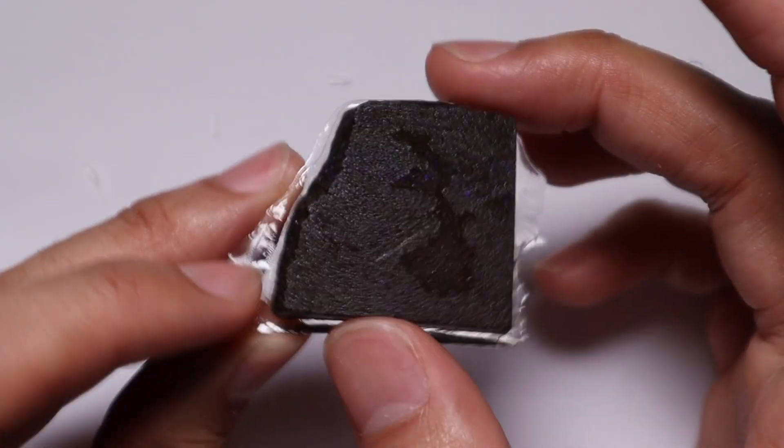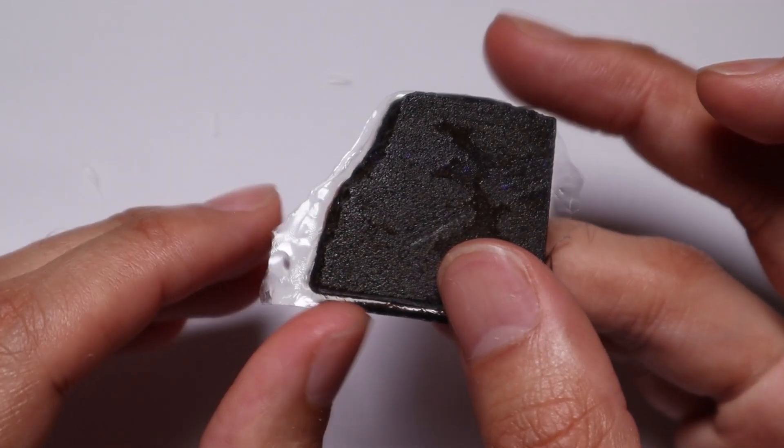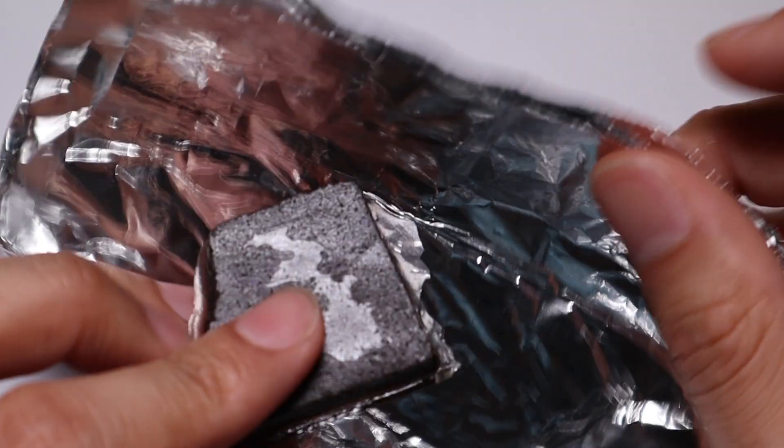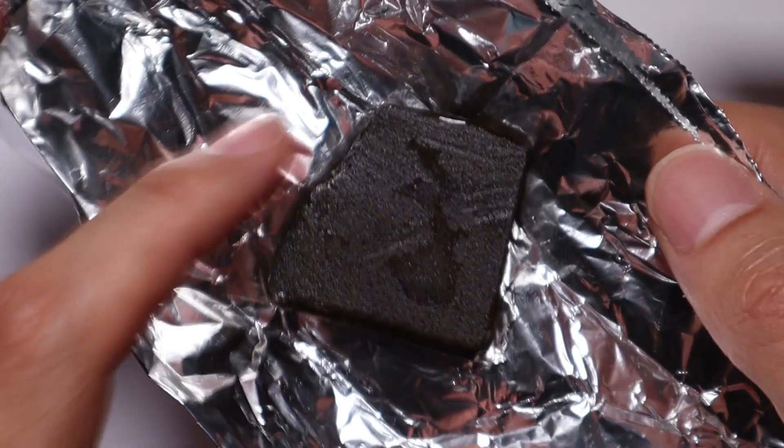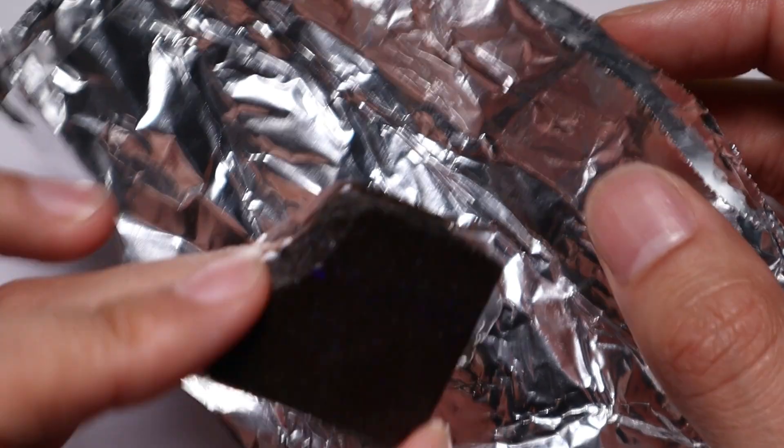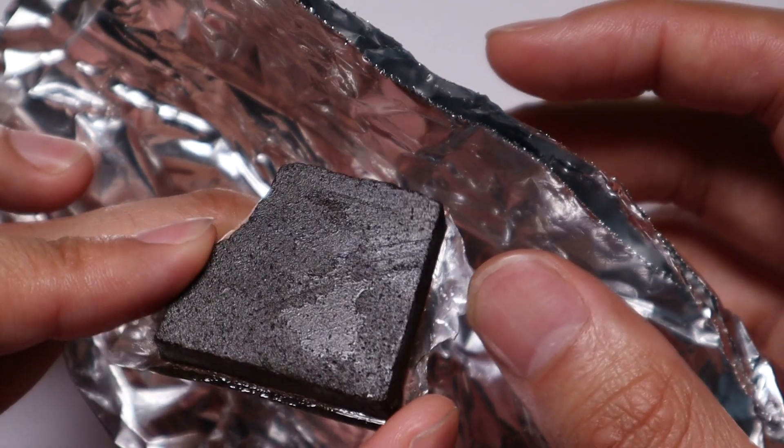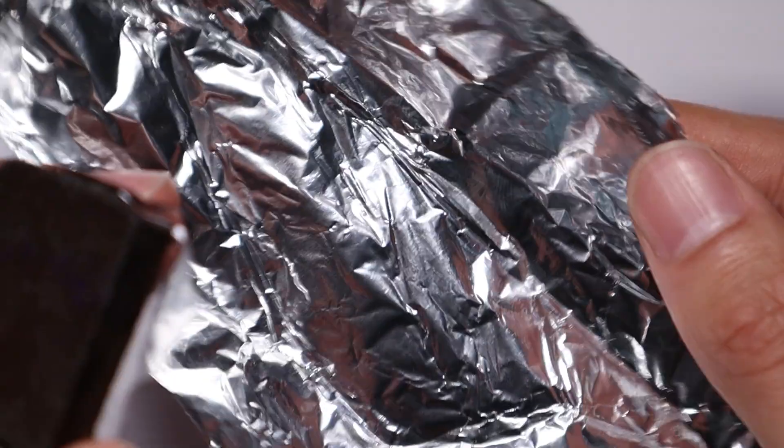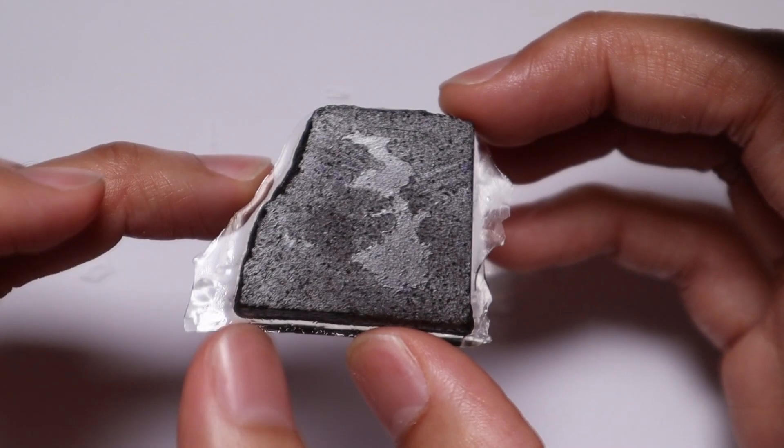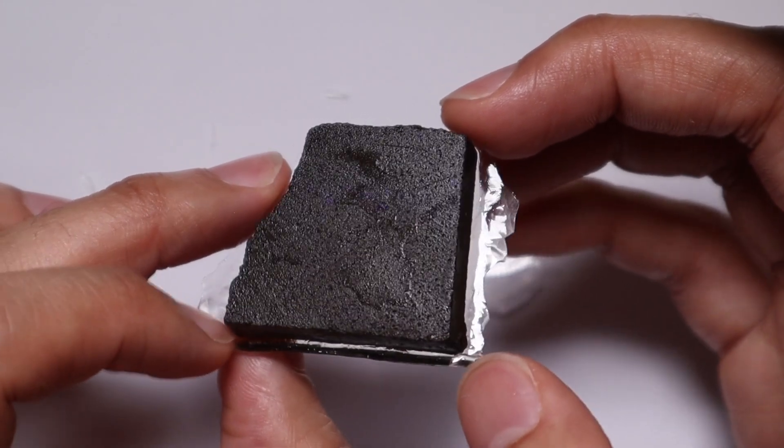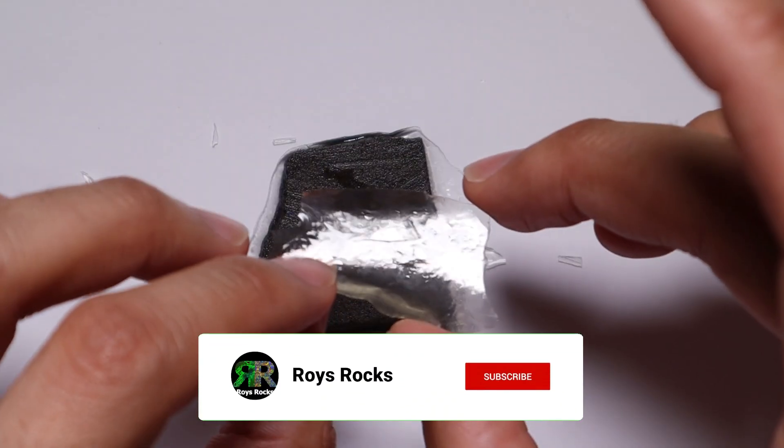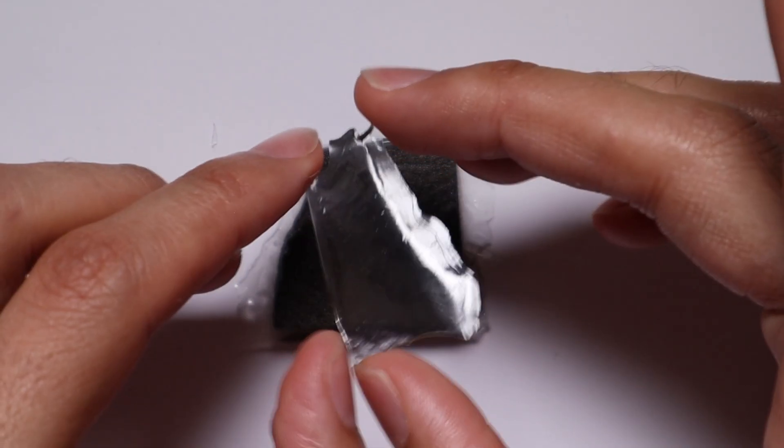It certainly does penetrate and it certainly does stabilize the stone. It's much harder and the treatment has definitely gone all the way through, making it really heavy. A little bit tricky and handling this is actually incredibly dangerous, because these edges are quite sharp and jagged. I actually think I've got some shards of it in my hands after doing those snaps. I should also mention, once you've got it in the foil and baked, if you find that it's stuck to the foil, just let it cool to room temperature and then it will just release itself. Don't panic and try to yank it off or anything. While it's hot, this is still a thermoplastic and so it's very grippy. Just let it cool all the way off and then just peel it off. You'll see that nothing gets left behind on the foil. It will very much stick to the rock. Anyway, it was worth a try. Good suggestions from people. I'm always willing to try it, but it's probably not the one for me. So onto the next one. Before I cut myself, I better put this down and I've got to work on another one, which I think will be the one. So I'll see you in that next video.